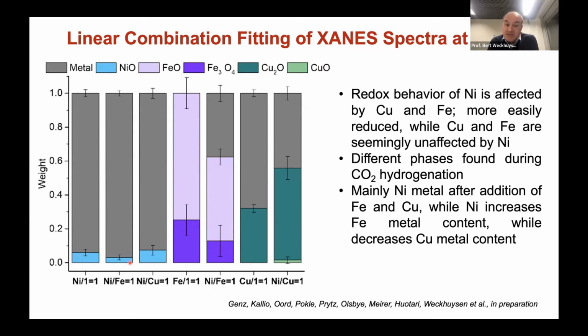But when you have copper, you see a little bit, but I would say that is still within the error. But you have huge changes in the copper and iron phase relative to what you see with the nickel. This is measured CO2 hydrogenation at 400 degrees C.